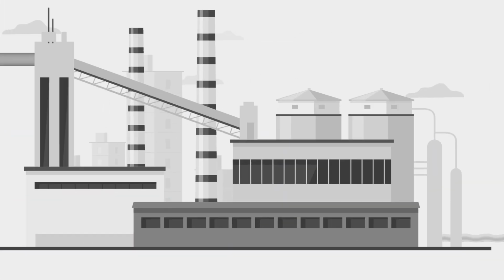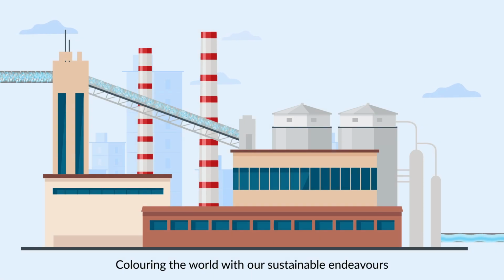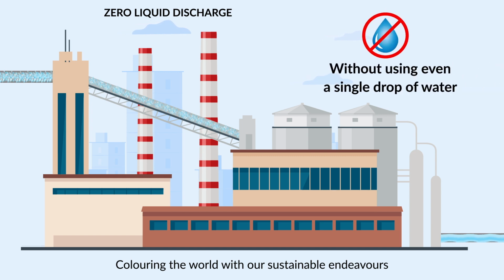The wash flakes are conveyed to silos, which undergo crystallization and drying to remove moisture. From here, it goes to the extruder where color master batches are added by an autodoser and the molten filament absorbs the desired color without a single drop of water, ensuring the best sustainable practices. The result is a staggering 50 different colored fibers produced using this process, thereby ensuring zero effluent discharge.